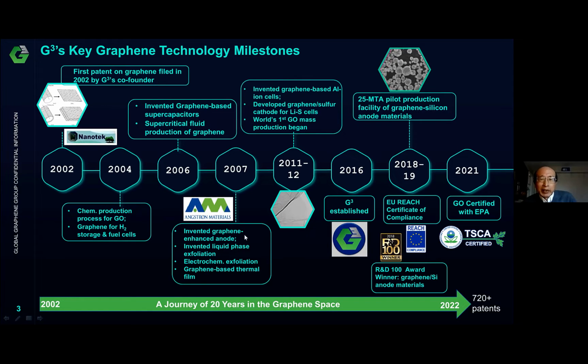And then along the way, we invented the graphene-enhanced anode. And then we are the ones who invented the so-called liquid phase exfoliation, and also electrochemical exfoliation of graphene, and also the graphene-based thermal films. And yes, we also invented the graphene-based aluminum-ion cell. We had a very strong IP position here. And we also work on sulfur cathode, graphene-enabled sulfur cathode, etc. In 2016, we finally incorporated or integrated several companies into this Global Graphene Group. And this is where we stand right now.